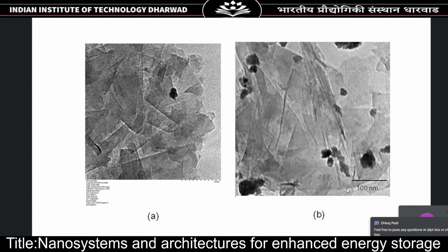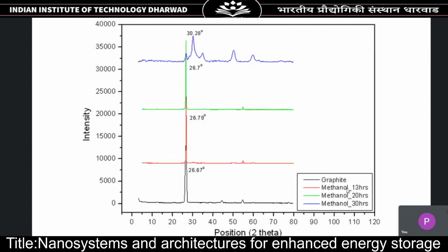This is the TEM image, high magnification of the exfoliated graphene. You can clearly see two things. One is that the number of layers of graphene is very few, and also there is a good amount of transparency. That shows that exfoliation has happened very well. And this is the XRD plot of the graphene. We have taken graphite and exfoliated in methanol for 13 hours, 20 hours, and 30 hours. You can see that the structure exfoliated in methanol for 30 hours has developed a very good XRD structure as compared to the other plots.